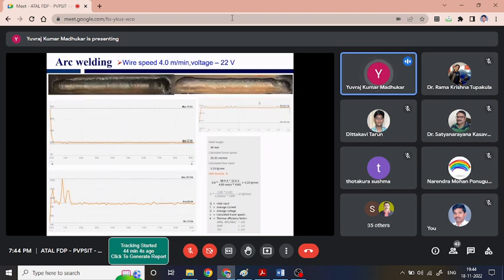However, the current has to be as stable as possible as well. We need to find the optimum parameters for the deposition. For example, in the other case, when we set the wire feed rate to 4 meters per minute and the commanded voltage to 22 volt, here we are getting such a nice deposition, no spatter, nothing over here. And here also we could see, once the voltage has been stabilized, the current became almost stable as well. Because of that, we could see a very nice deposition.